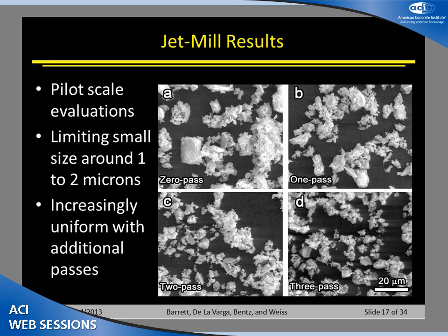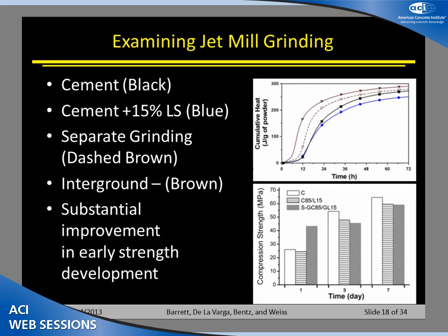After about 2 to 3 passes, we can get down to a material in the 1 to 2 micron range in particle size, and then continued collisions really don't get the material any smaller than that. And this is probably a very active material, which we'll see from some of the data that'll be shown a little bit later. So with the original material we started out with, after 1 pass, 2 passes, 3 passes, we can greatly reduce the size of the particles, and this can have great impact on the reactivity of those materials.